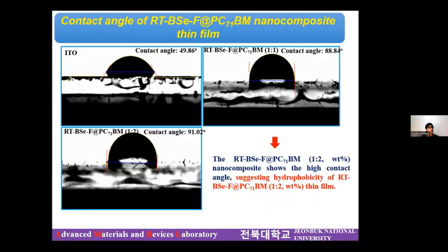And since we are applying it for the photocatalytic application, it is very significant to know the hydrophobicity of the material. If the material is hydrophilic in nature, it might get dissolved in the solution. So we performed the contact angle measurement, and we found a higher contact angle of around 91.02 degrees, which shows that our material is hydrophobic and certainly applicable for the photocatalytic requirements.